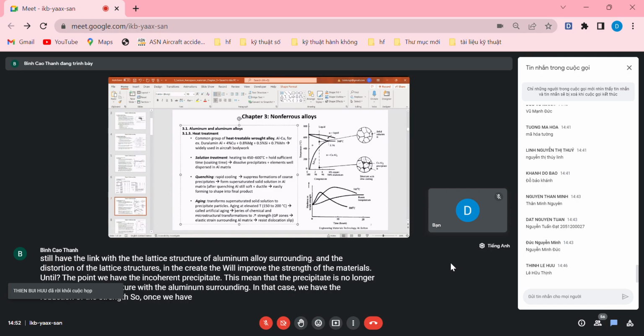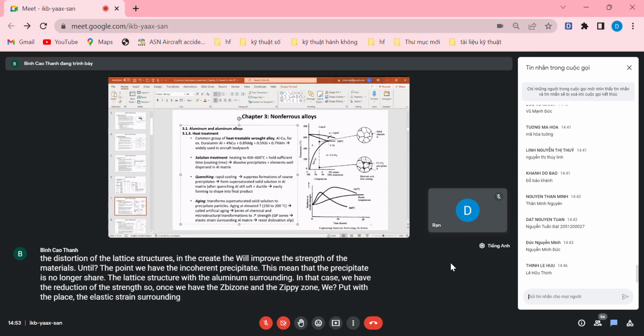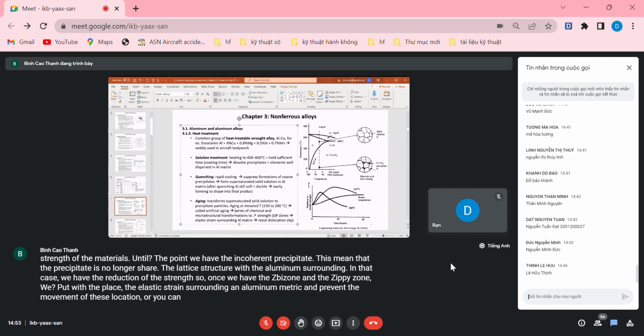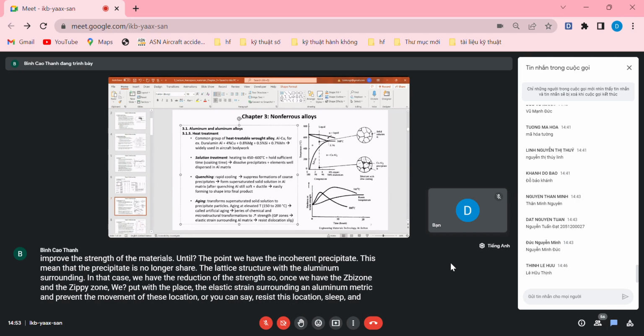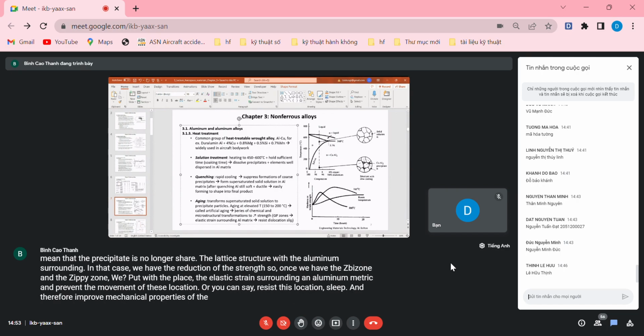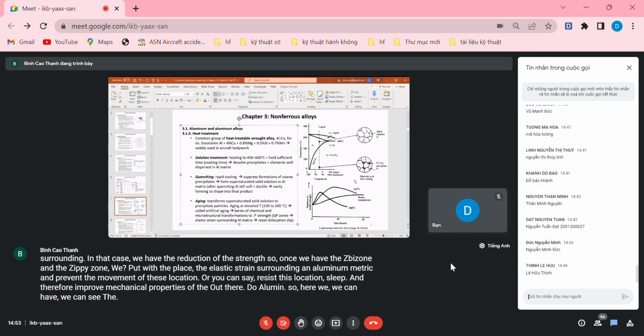So once we have the GP zone, it will place elastic strain on the surrounding aluminum matrix and prevent the movement of dislocations, or you can say resist dislocation slip, and therefore improve the mechanical properties of the duralumin. So here we can see the effect of changing aging temperatures on the properties of the aluminum alloys.